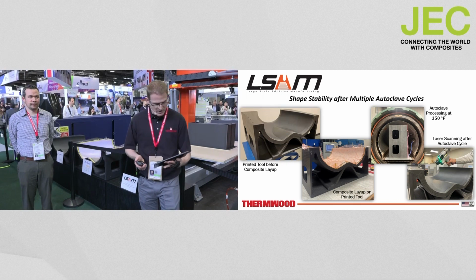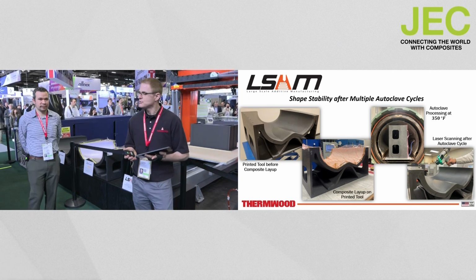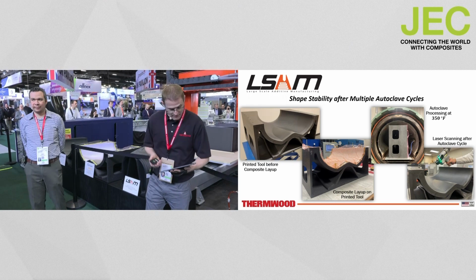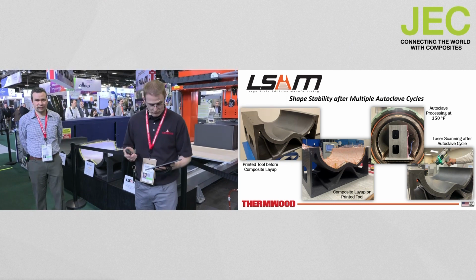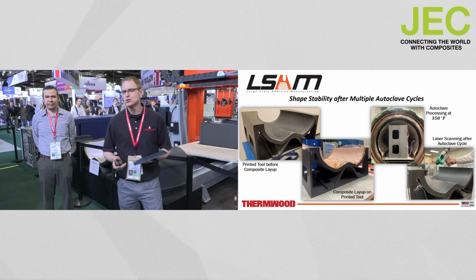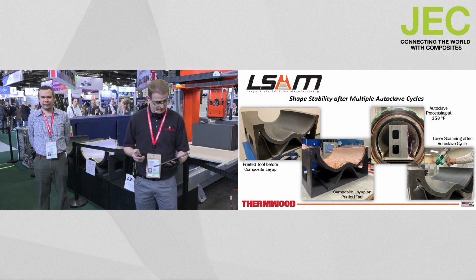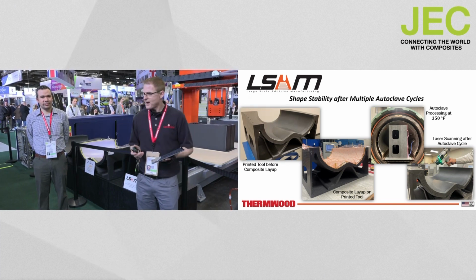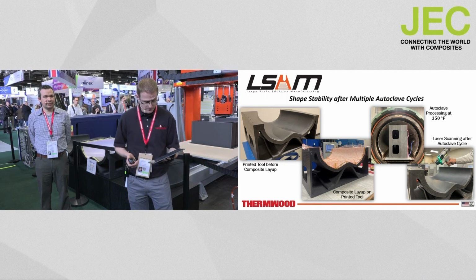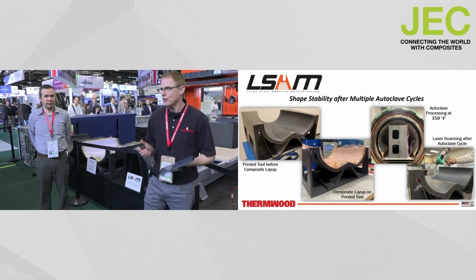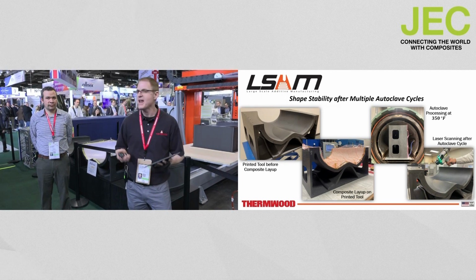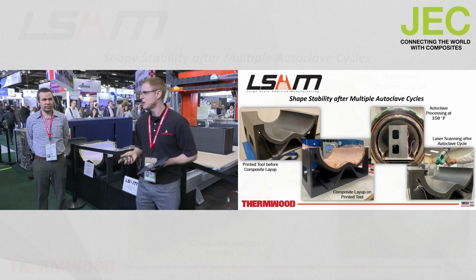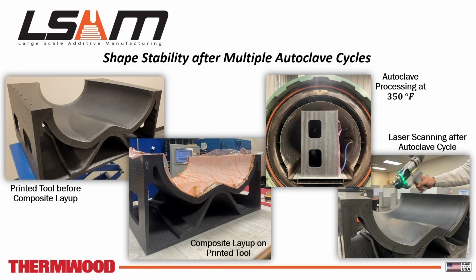I'd also like to mention that this study shows that LSAM printed tools have excellent shape stability after multiple autoclave cycles, showing that longevity can be expected. So with all these factors considered and understood, we can achieve first-time right printed tools that have vacuum integrity directly off the machine and produce dimensionally correct finished parts.